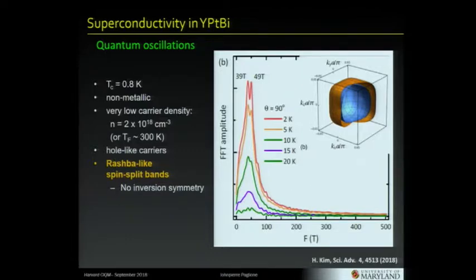What's FFT? Fast Fourier transform amplitude. No, oh, F of t, sorry. This is the frequency in Tesla. So it's the Shubnikov-de Haas frequency. So 50 Tesla is quite small. I should say that also matches the carrier density measured, let's say, from Hall effect. So it's a very small frequency, which means a very small Fermi surface.